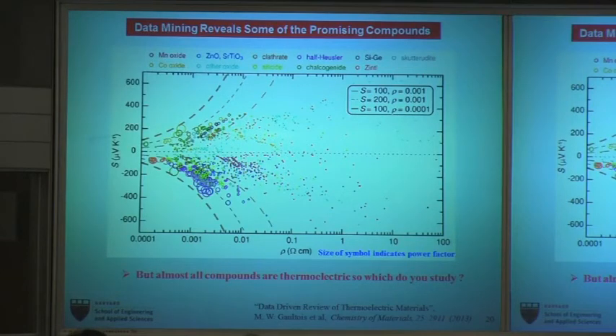Material out here, this includes some of the materials I've worked on, by the way. There's no hope of using those in real practical applications. They might tell you something about underlying physics. But the reason you have to use this sort of approach together with, if you like, the abundance is that almost all compounds are thermoelectric. In fact, it's often used, or was used in the past, to measure, you'd measure the Seebeck coefficient to find out what the defect concentration was, for instance, in a semiconductor or a ceramic material or inorganic material. So you have to do studies like this.